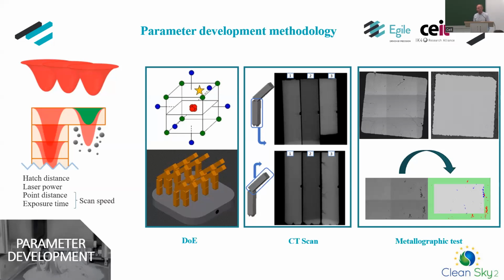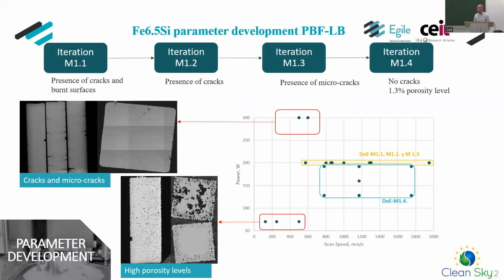The first soft magnetic material we started working with, as our colleagues from CEIT have explained, has been the iron silicon, a very difficult material to additive manufacture. Four different iterations needed to be done in order to avoid cracks and micro cracks in these test tubes.